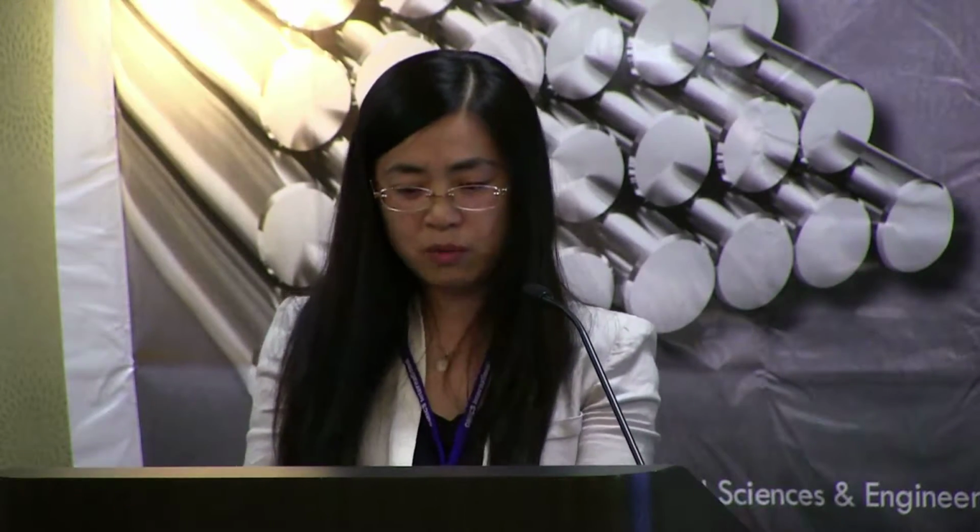So droplet condensation on the wetted spider silk can be controlled by the composition of the surface energy gradient and the Laplace pressure. The surface energy gradient is introduced by the roughness gradient, and the Laplace pressure results from the curvature gradient. So droplets can be driven directionally by the composition of both gradients.